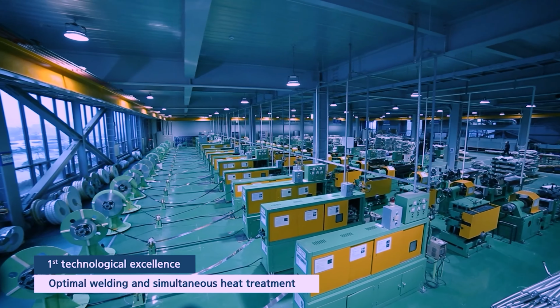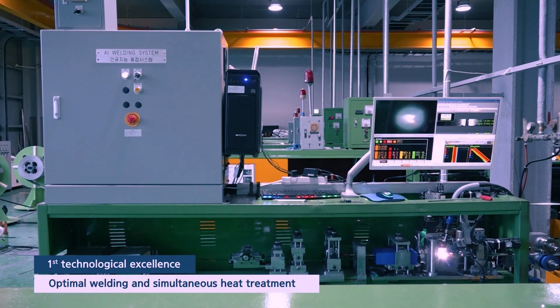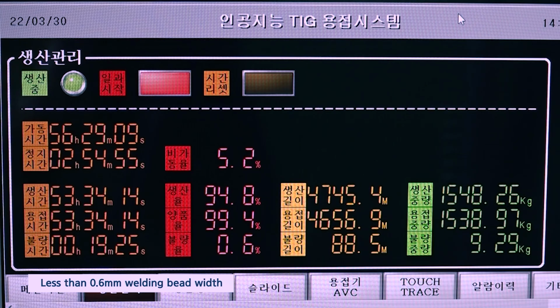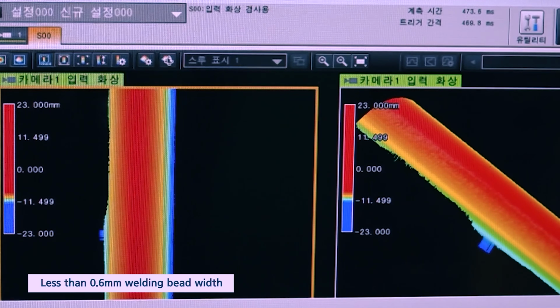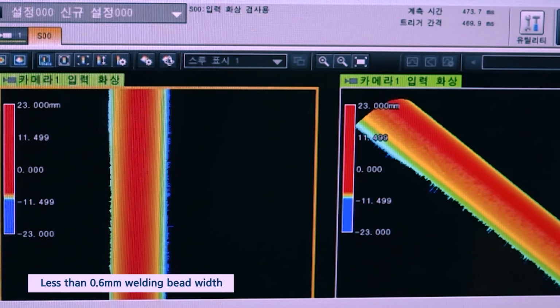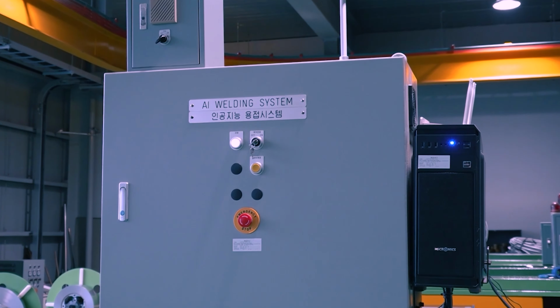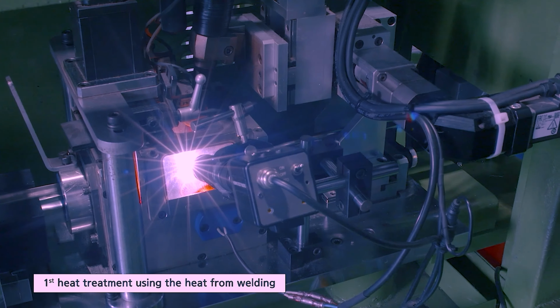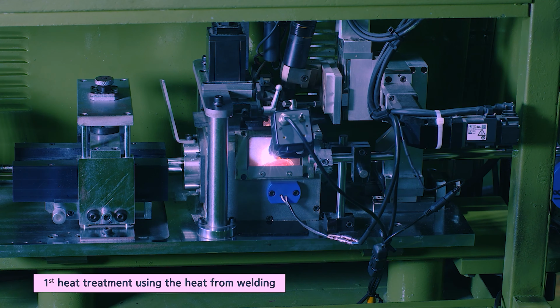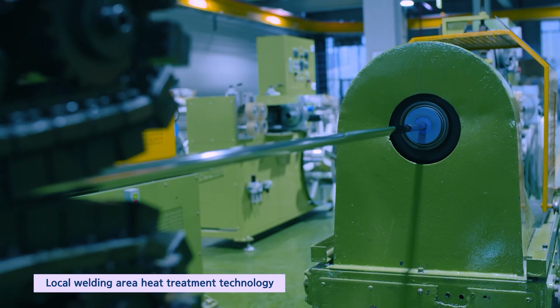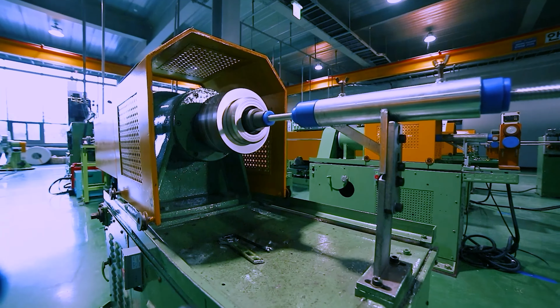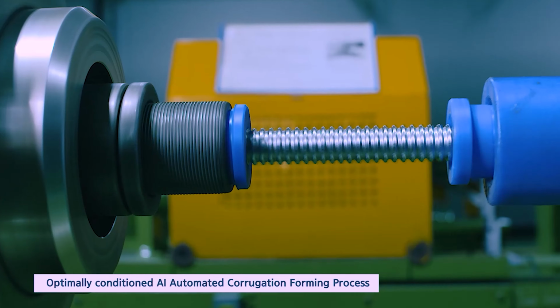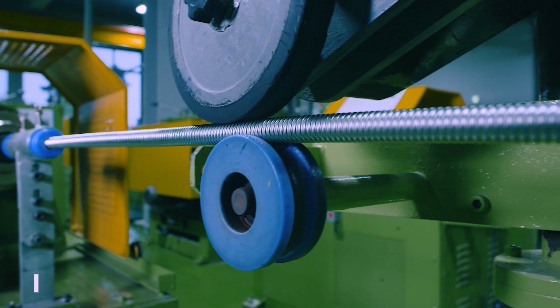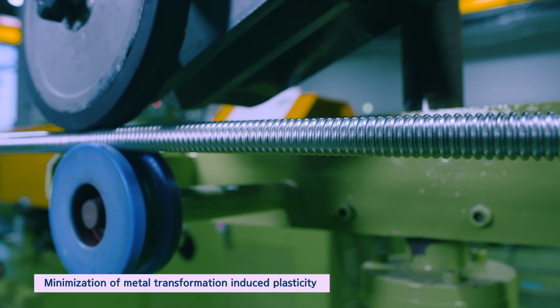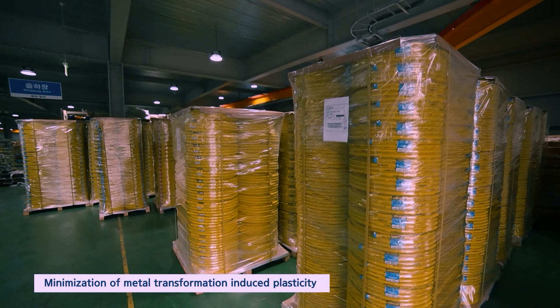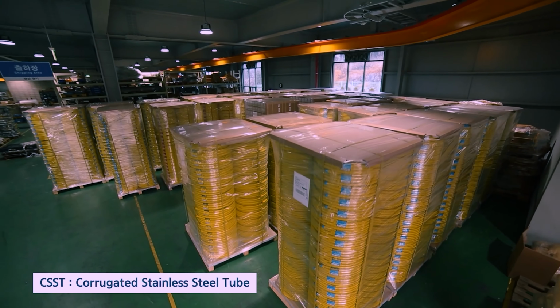The flexible pipe that Dongha manufactures has a CSST welding bead width of less than 0.6 millimeters. The thickness of the welding bead is the same as that of the parent material. After the first local heat treatment on the weld bead and welding heat affected area by using welding heat, simultaneously with welding, the corrugation forming process is done under the optimal condition. So the transformation-induced plasticity that may occur during the corrugation forming was minimized in this CSST.